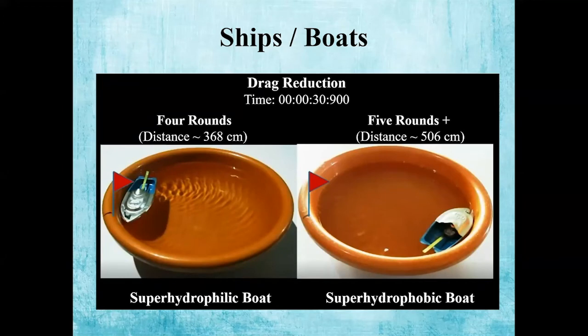It is again an idea experiment, not to be applied directly on big ships, but it is one application of superhydrophobic coating for drag reduction. We bought two small boats from the market. Okay, sorry, I will go faster. We coated the bottom part of the boat. You can see on the right side is the superhydrophobic boat. In 30 seconds, the superhydrophobic boat can cover 506 centimeters, but the non-coated one covers only 368 centimeters. So superhydrophobic coatings can be used for drag reduction.